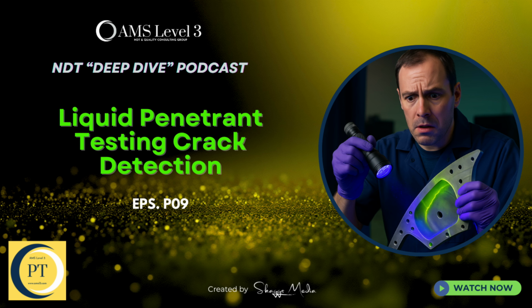These materials can be very susceptible to something called stress corrosion cracking. And it turns out that if even tiny trace amounts of certain elements, specifically sulfur or halogens like chlorides and fluorides, are left behind in a crack or crevice after the penetrant test, when that part goes into service, especially at high temperatures, those residual elements can initiate or accelerate corrosion and cracking. It's like leaving a tiny chemical attacker behind.